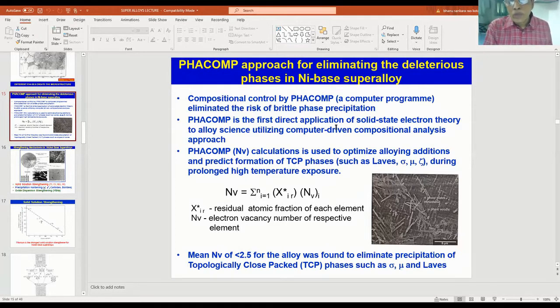When melting and other processing is taking place, the phase computation calculations are done for each of the alloying elements that are present. Here you see that there is an equation. The atomic fraction of each element is taken into account and multiplied by the electron vacancy number of the respective element, and this is calculated for each element, and the summation is done for all elements, and we get Nv, that is, for that alloy, a mean Nv of less than 2.5 was found to eliminate precipitation of TCP phases such as sigma, mu, and Laves.